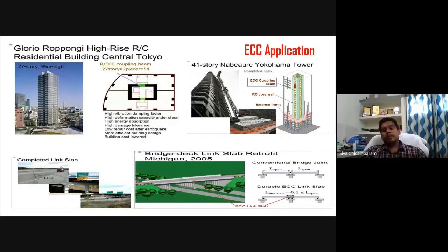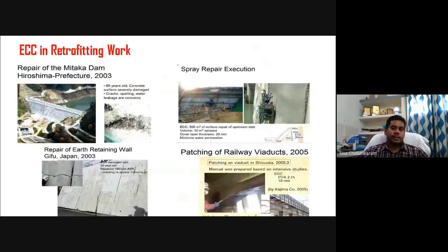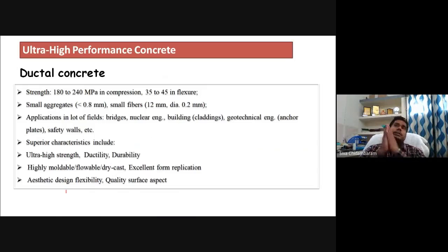When you cross a bridge from one span to another in India, you will feel a certain amount of vibration, because the gap between the spans creates that vibration, as we are not treating it perfectly. So what they have done is use ECC exactly between the spans. They have converted the connection like this, and it becomes a wonderfully smooth line. You can also use these kinds of retrofitting materials in bridges, dams, buildings, etc. When you use these composites in the joint region, you can eliminate the need for closely spaced stirrups, and you can increase the shear carrying capacity, energy dissipation capacity, damping capacity and damage tolerance capacity. So your building will go through a larger amount of deformation with significant damage, so that it can be retrofitted.